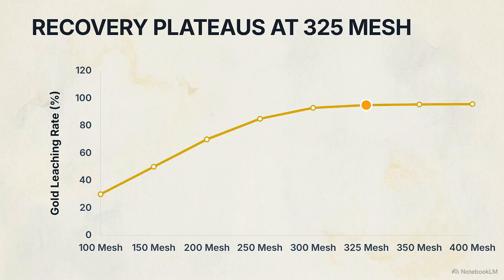As the ore is ground finer, the gold leaching rate increases sharply as more mineral surfaces are exposed. Eventually, the curve flattens out. Finer grinding provides no significant boost, consuming energy for little gain. The optimal target is 325 mesh at 95%, maximizing recovery.